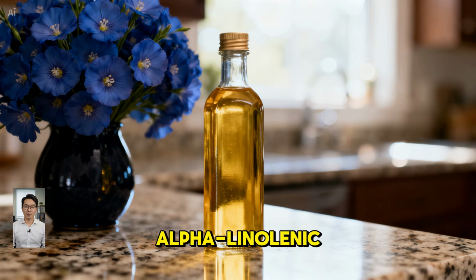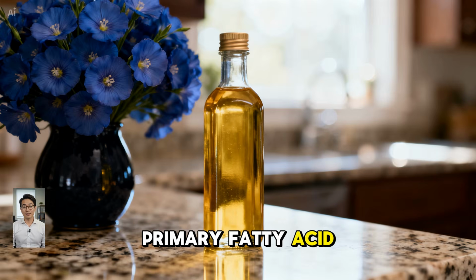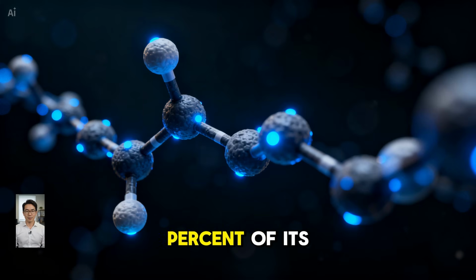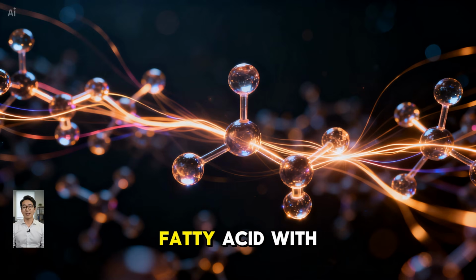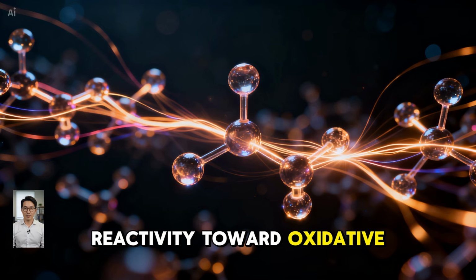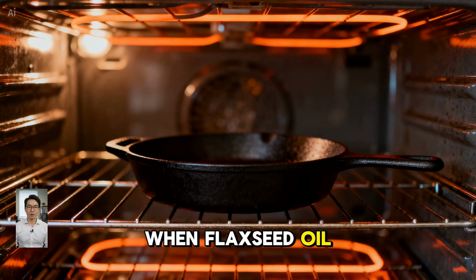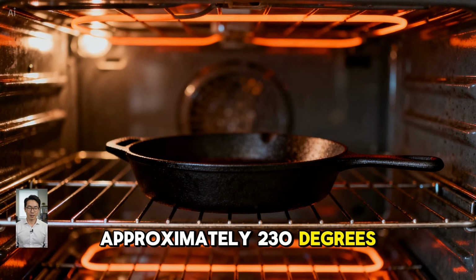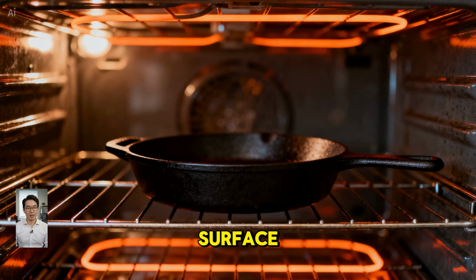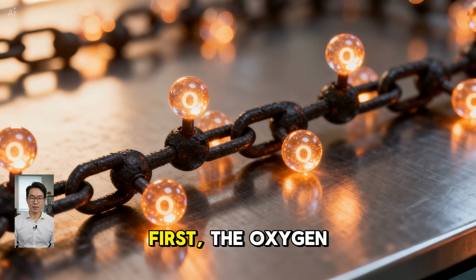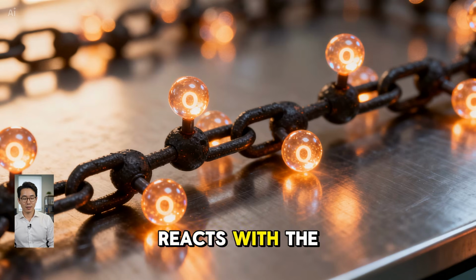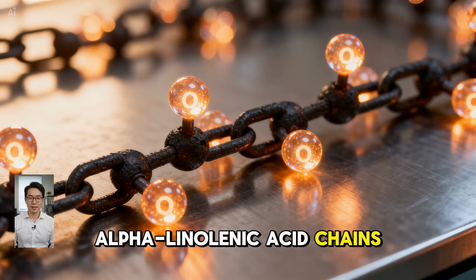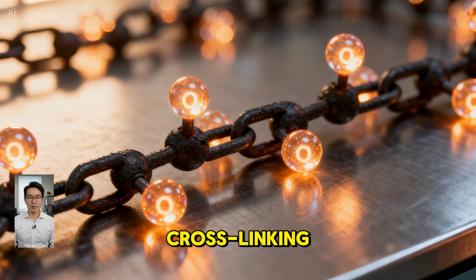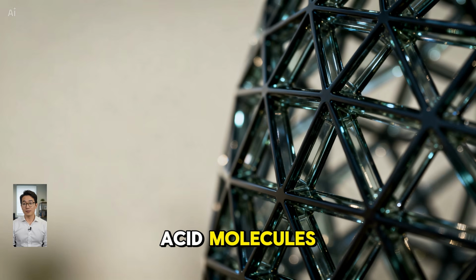Flaxseed oil contains alpha-linolenic acid as its primary fatty acid, comprising approximately 50 to 60% of its fatty acid content. Alpha-linolenic acid has 3 double bonds per molecule, making it a polyunsaturated fatty acid with exceptional reactivity toward oxidative polymerization. When flaxseed oil is heated to approximately 230 degrees Celsius in the presence of the iron surface, 2 processes occur simultaneously. First, the oxygen in the oven atmosphere reacts with the double bonds in the alpha-linolenic acid chains, initiating a chain reaction of cross-linking between adjacent fatty acid molecules.